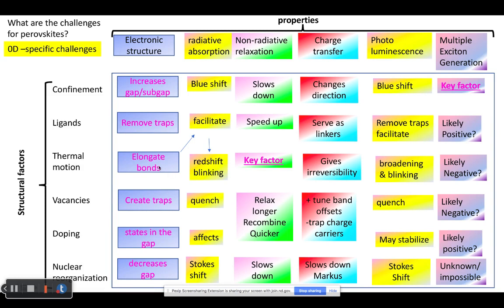So thermal motion is expected to elongate chemical bonds, and it affects spectra by adding thermal broadening, and also elongation of bonds may induce blinking. For non-radiative relaxation, thermal motion is a key factor because at 0 K, the non-radiative relaxation vanishes. For charge transfer, the motion of nuclei provides irreversibility. So if it did transfer, it doesn't transfer back up in energy. For photoluminescence, it also adds broadening and the effect of blinking, which is unfavorable.